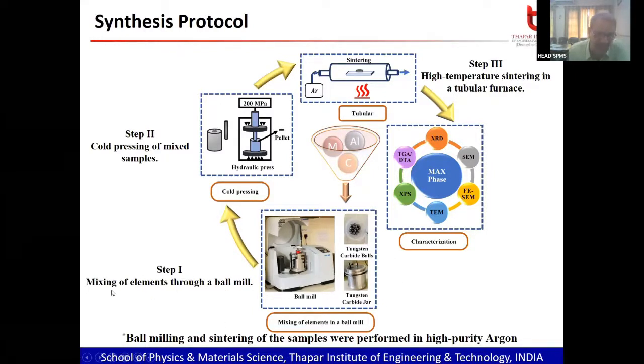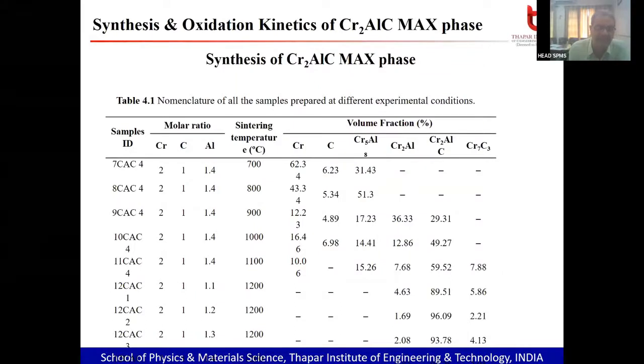In step 1, mixing of the elements under an inert atmosphere is done, followed by compacting, and in the third step we are going to sinter it at very high temperature. So it's not so easy to synthesize MAX phases. After doing hundreds of experiments, not 1, 2, 3, 4, hundreds of experiments, we could succeed in synthesizing the MAX phases. We were getting carbides, but we have to optimize the conditions here.